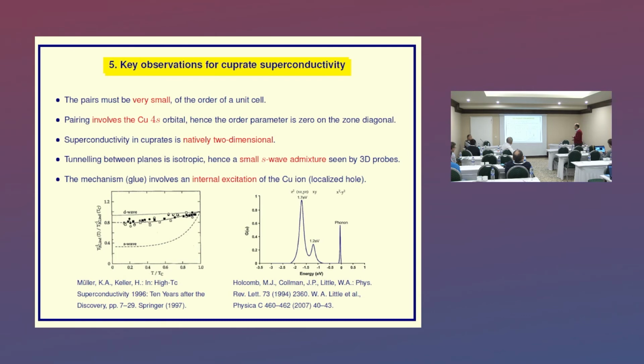You see, this is an NMR, I believe, probe. So a bulk 3D probe sees a little admixture. You see, this is a D wave line, this is an S wave line, and even at that time, Alex Müller pointed out that pure D wave superconductivity in cuprates is found only by surface probes. If you have a bulk probe, then you will have a small S admixture. And this fits perfectly into this picture of very small pairs tunneling point-like between the planes.